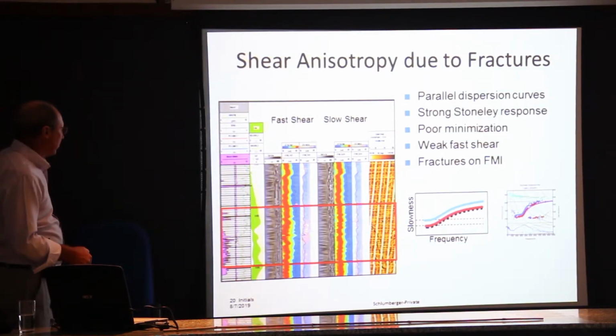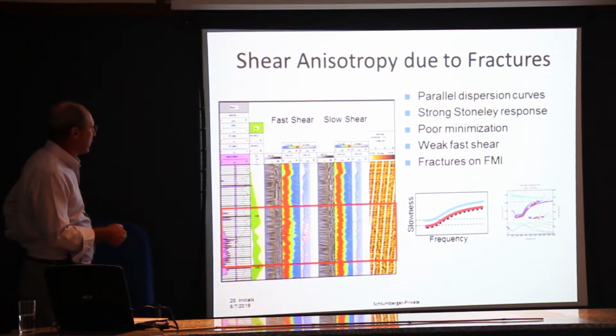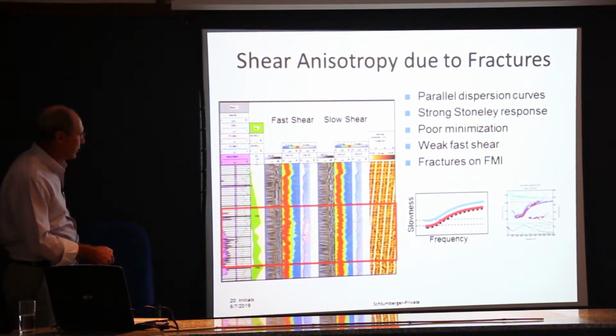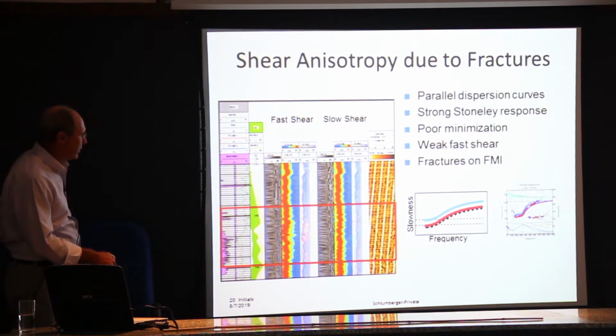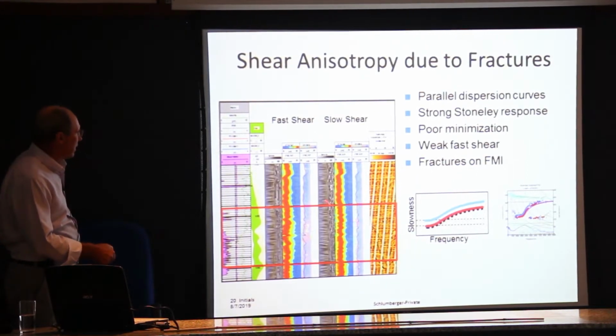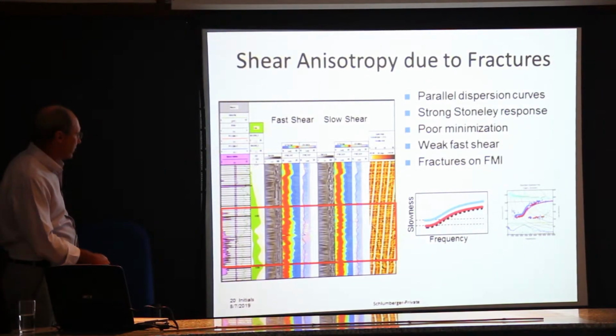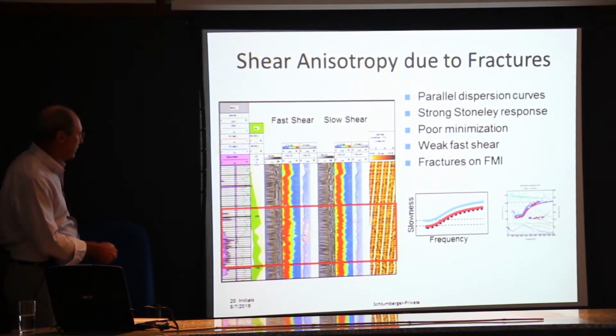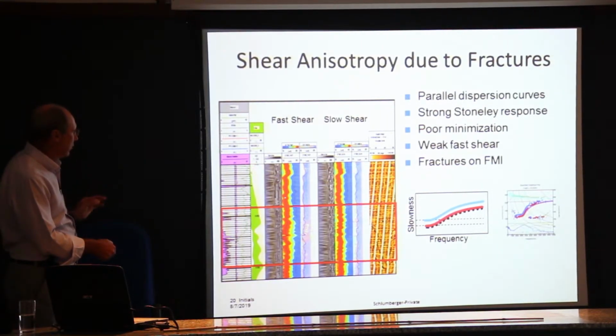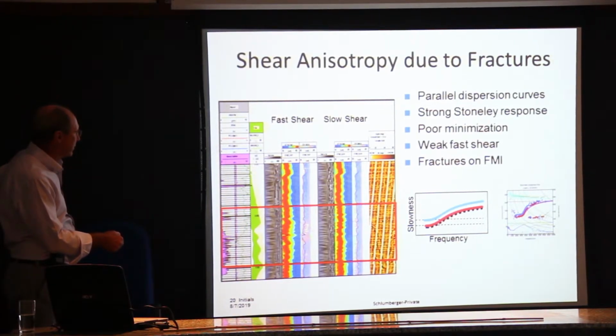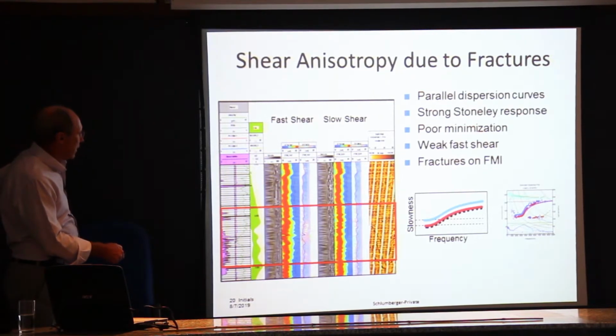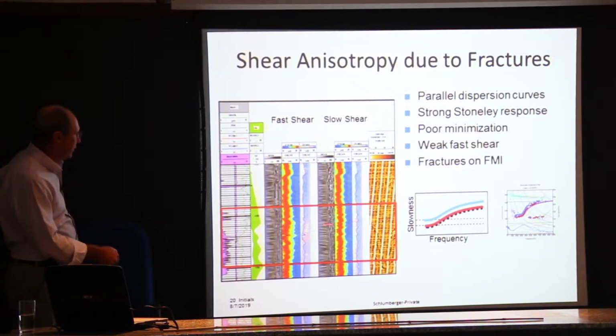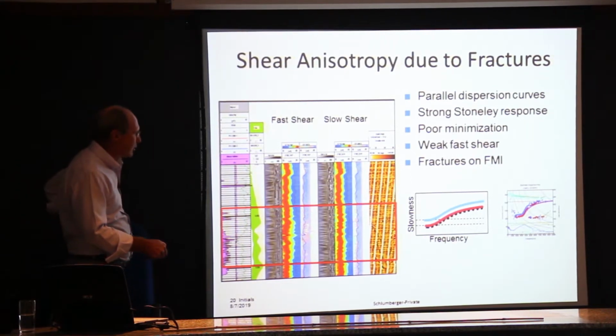So here's some results of some shear anisotropy in a fractured interval. So this is an image log, and you can see these fractures right here. This is the fast shear, this is the semblance plot. Red is high semblance, so you're getting very good cross correlation here. This is slowness on this axis. And this is the slow shear here. And what you find when you have the fracture, you get a difference between the fast and the slow shear.